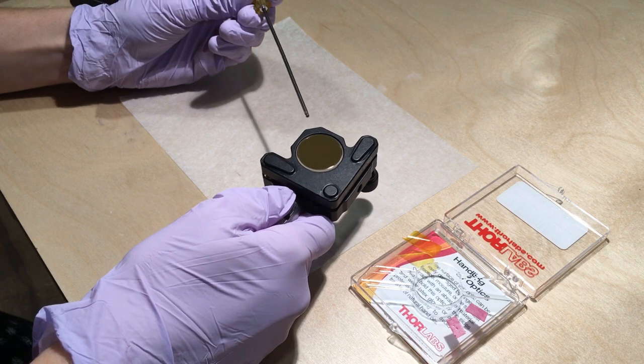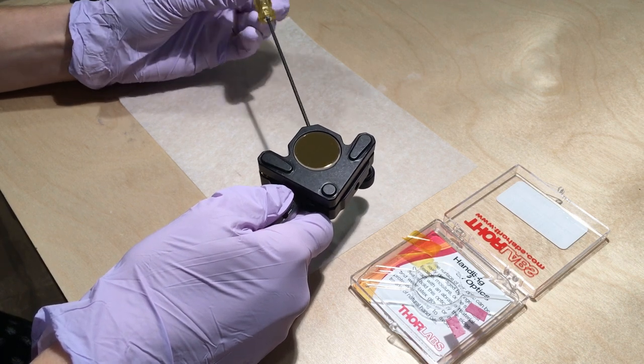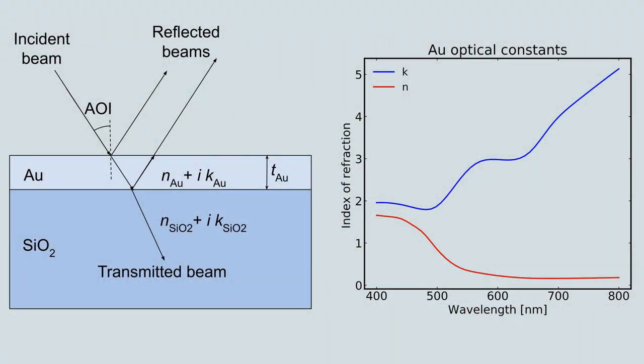The spectrum is reliably calculated as a single thin layer on a dielectric substrate. We use standard matrix methods to compute the transmission and reflection of electromagnetic waves in a stratified medium. The model parameters are the thickness of the layers, the angle of incidence, and the real and imaginary refractive indices of the layer materials.